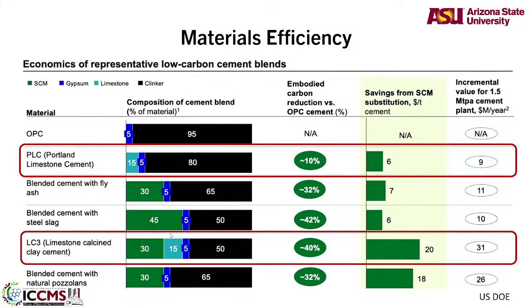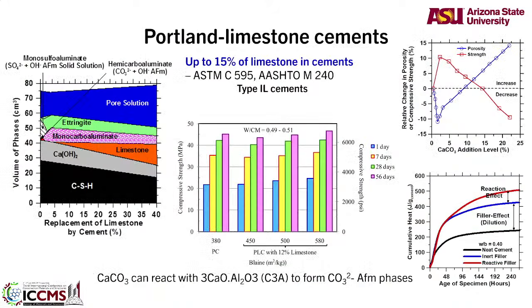So limestone calcined clay cements here, which is quite efficient in carbon reduction. Now the question is, how do we extend this further and how do we apply it? So let's talk about a few of those things. Portland limestone cements, the science has been proven for quite a long time. 10-15% of limestone ground back into the cement so that you can save that 15% clinker. Great strategy. What happens is that a little amount of that limestone can react with the aluminates available to form mono-hemi-carbonates, in addition to the CSH gel that you form to give you additional properties. You save extra cement. There's a bunch of theory as to how this happens, but you don't have to worry too much about it. This can be done.